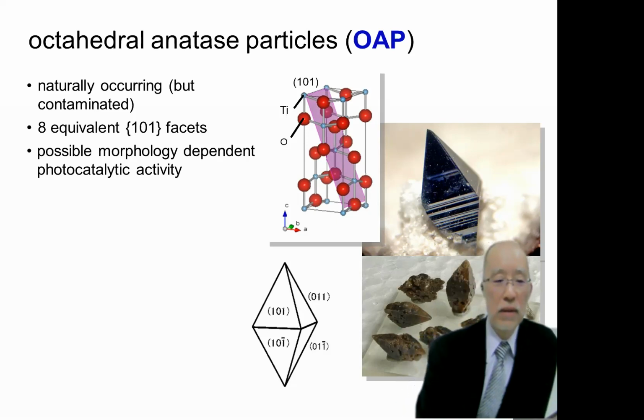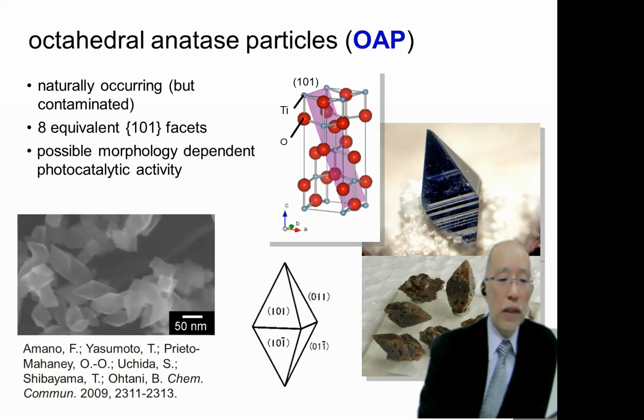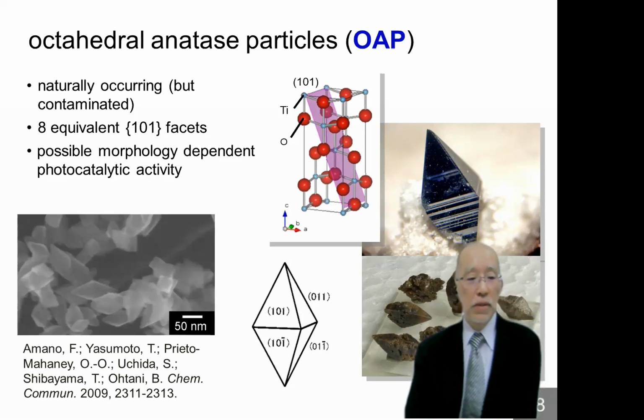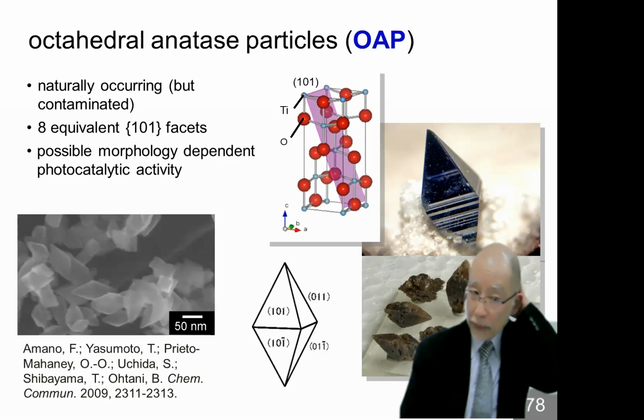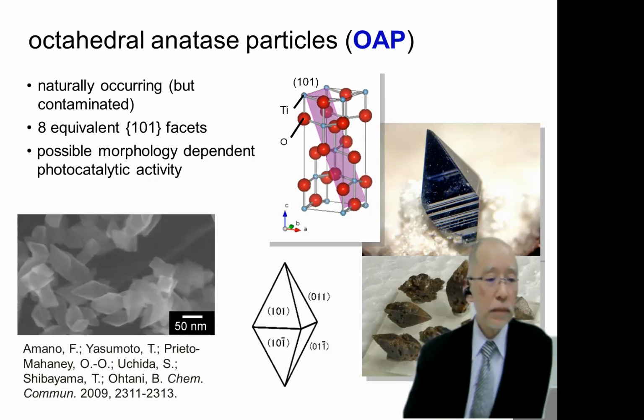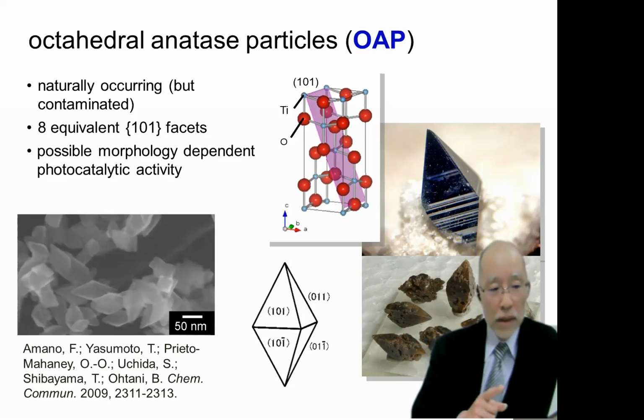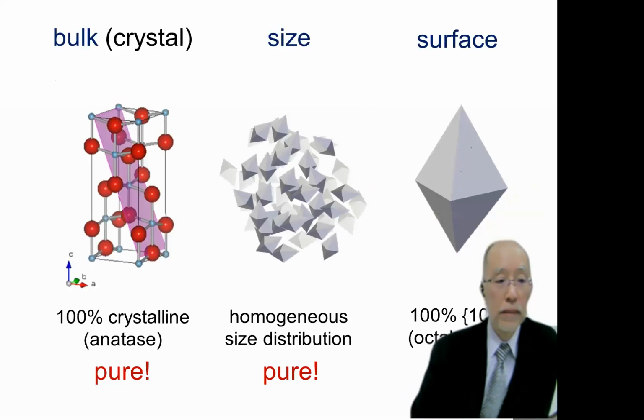And this is a natural one, but we can prepare this octahedral particle. First, Yasumoto-kun and Amano sensei prepared this from the titanium nanowires. And that is a very small particle, about 20 or 50 nanometer size, but with a very high content of octahedral particles exposing only one type of facet, 101.